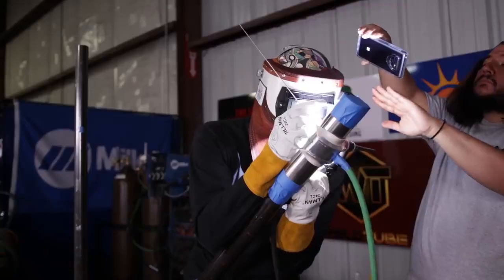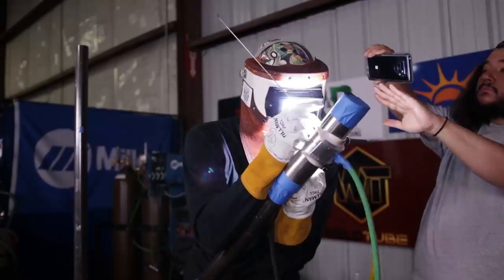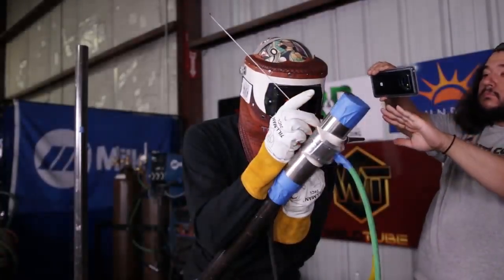I'm looking. My line of sight is lined up with the leading edge of the weld puddle, so I can see the external leading edge and the internal leading edge. The TIG torch heats up the external leading edge, and a split second later the internal leading edge turns to a liquid. However, the weld puddle has washed out internally. So when the internal leading edge turns to a liquid, that's when I take the tip of my filler metal and touch the internal leading edge that is liquid.